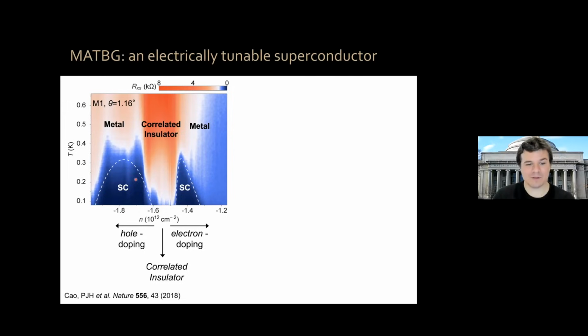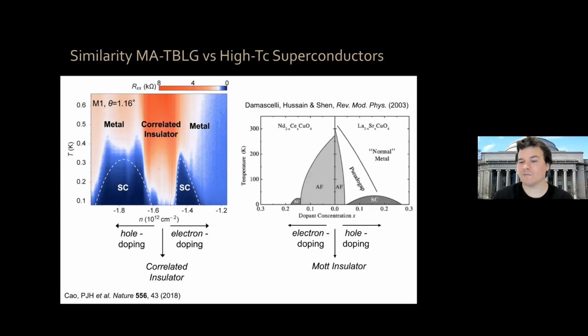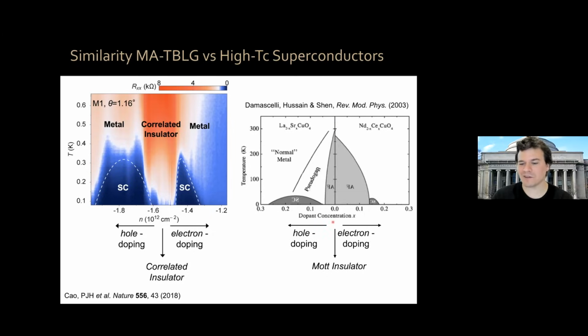Now, the moment my students showed me this data, I was fascinated, because this instantaneously reminded me of the hundreds and hundreds of times that I have seen phase diagrams such as this, okay? This is the phase diagram of the high temperature cuprate superconductor family, okay? They sort of get the electron doping and hole doping wrong in this diagram. Let me flip it for you. Here it goes. Here it's correct, okay? Now, as I mentioned earlier, 0 dopant concentration means 1 electron per unit cell, okay? In a cuprate, that is a Mott insulator, which is a correlated insulator. You add holes and you get a superconducting dome. If instead you add electrons, you also get another superconducting dome.